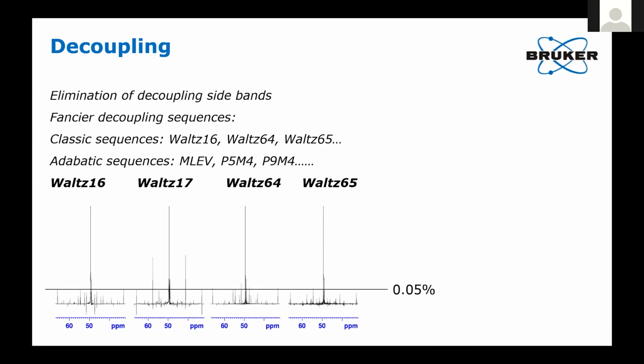One way is just getting fancier sequences. If you look here, we start on the left with a simple WALTZ-16. That gives us a sideband pattern. By the way, this is carbon-13 labeled methanol, so I get a huge peak, and so I see those small peaks. We're at about a factor of 10 below what would be a satellite height if you have more than one carbon in there.